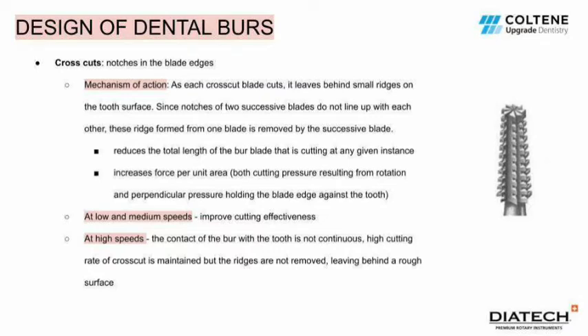This reduces the total length of the burr that is cutting at any given instant and increases the force per unit area due to both cutting pressure resulting from rotation and perpendicular pressure holding the blade edge against the tooth. At low and medium speeds, cross cuts improve cutting effectiveness, while at high speeds, the contact of the burr with the tooth is not continuous, and the high cutting rate of a cross-cut burr is maintained, but the ridges are not removed, leaving behind a rough surface.